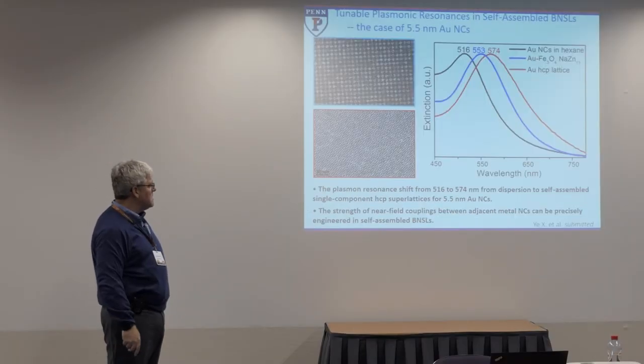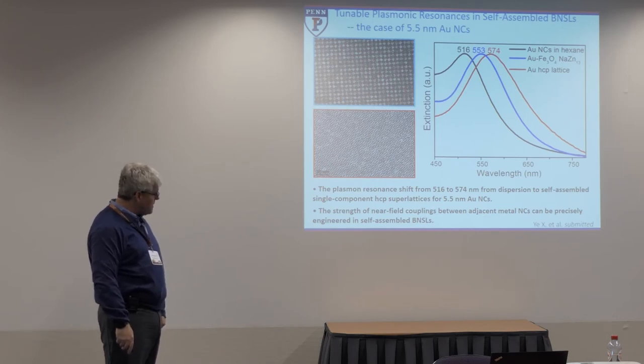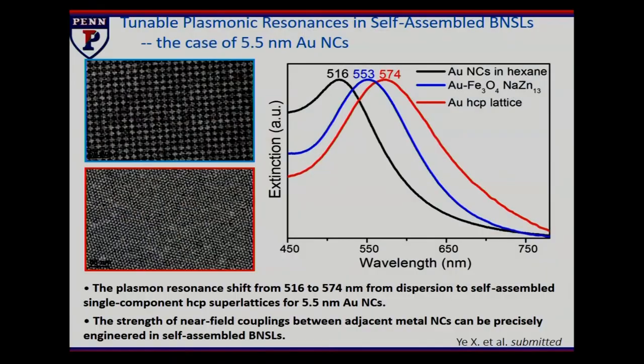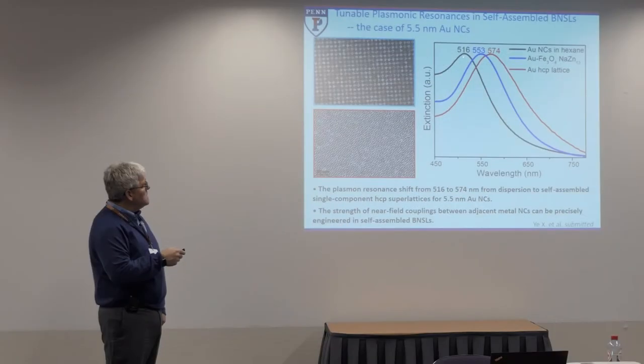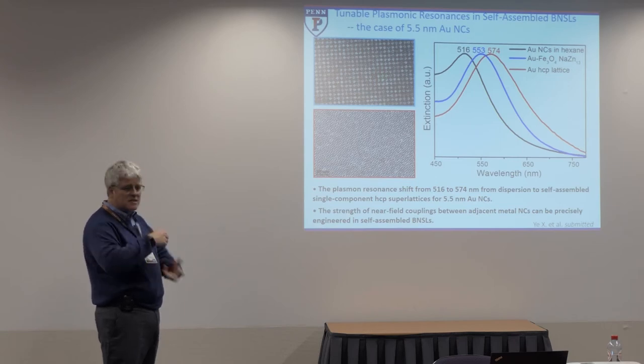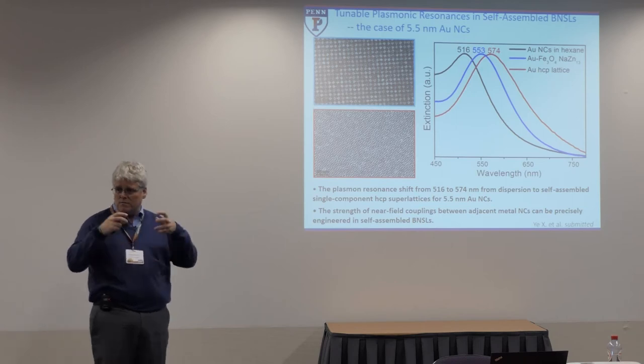So back to my comment near the first about how we want to be studying the inherent properties, not the defects, if we can. And so this kind of system, where you can do an ensemble measurement but then single particle measurements, are important pieces to help sort out exactly those interactions. These are the same components, but now organized with different symmetries. So the plasmonic resonance moves in its position because the symmetry and positions, the coupling between the different gold resonators, is changing as we change the crystal structure for the material. And so that's part of our thought again about designing metamaterials that allow tunable optical resonances by adjusting the interaction between the systems.